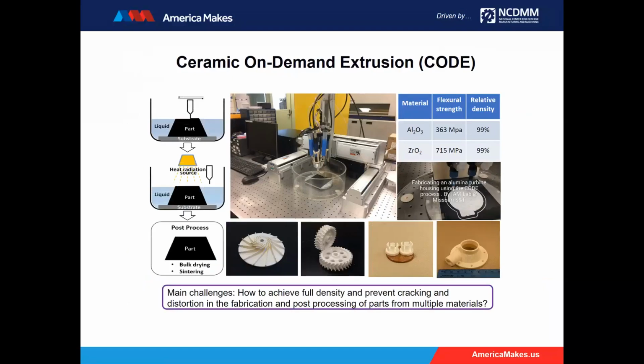So this process we call the ceramic on-demand extrusion process, and you can see that we have the schematics, we have the equipment, we have the parts made by this process: turbine impeller, gears, blower housing, thin wall parts. The part is made in a little tank, and every layer after it's built, this is not immersed into the liquid, but after the layer is built, the liquid is then added to flush with the surface to prevent uneven evaporation of water from the side.